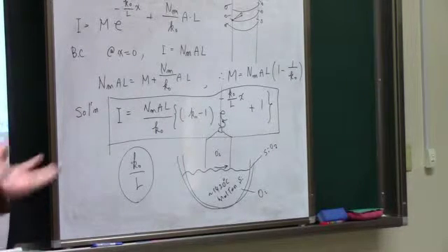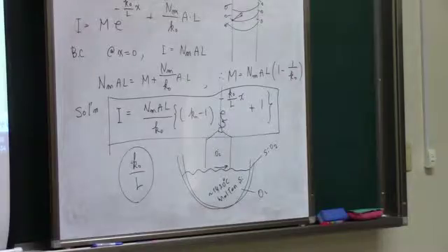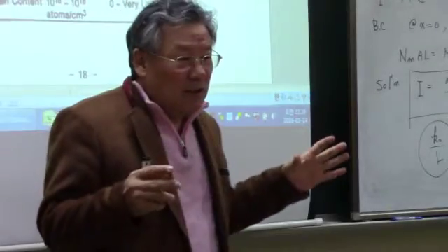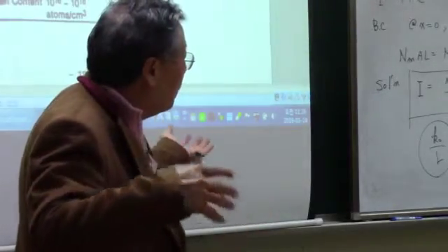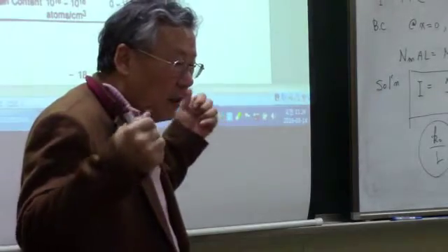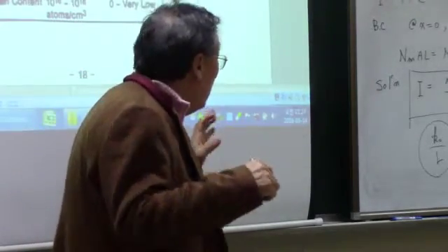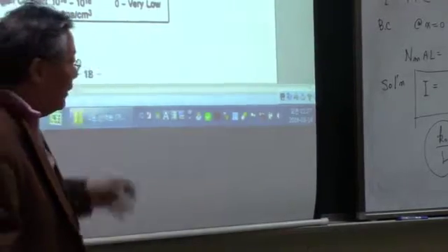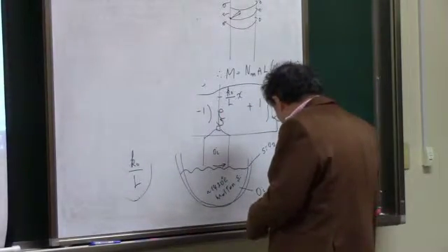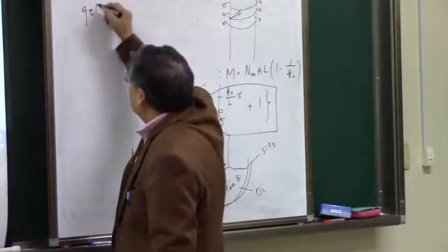But in most DRAM industrial processes, you really don't have to go for that high quality silicon. We just use the Czochralski silicon wafers, and we have means to get rid of this oxygen content in the Czochralski. That is called the gettering. Okay.